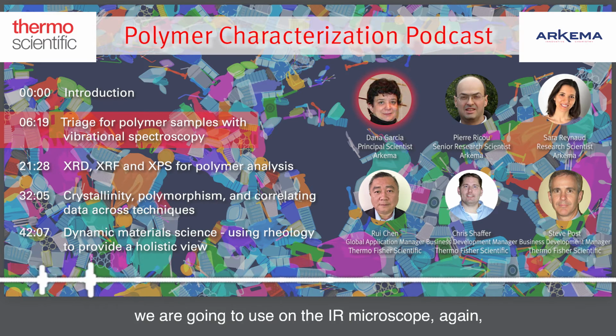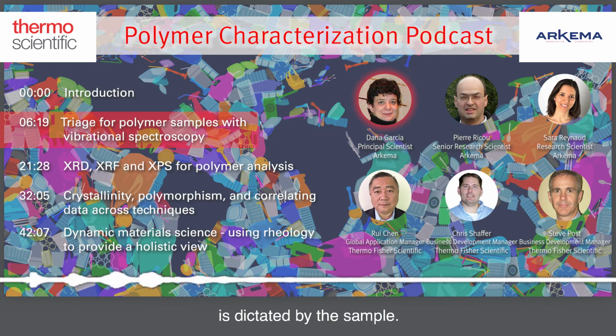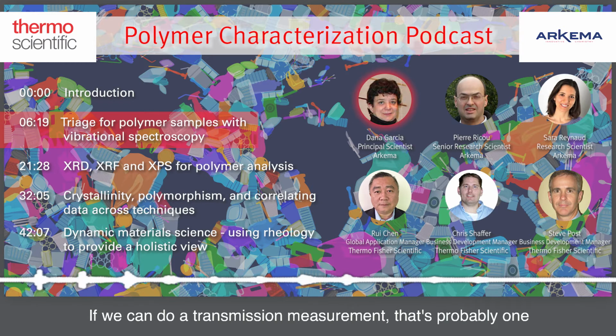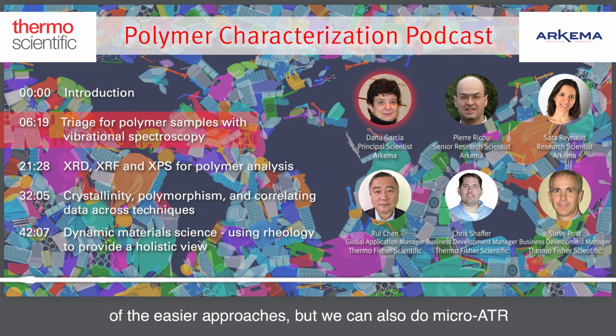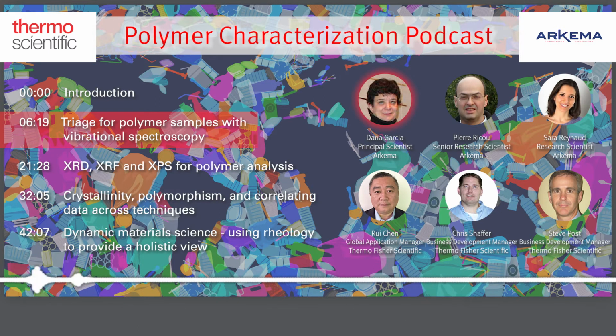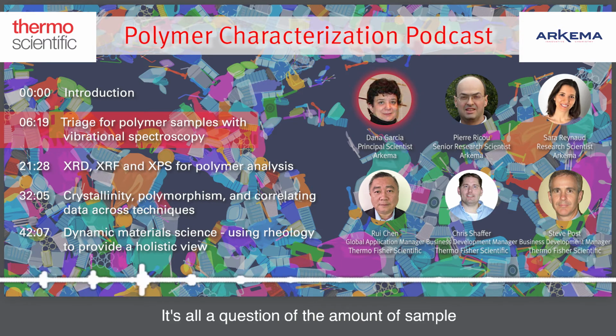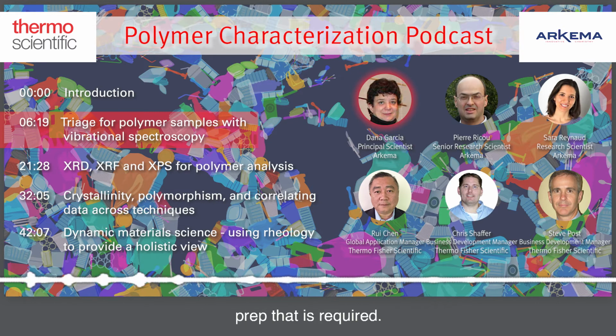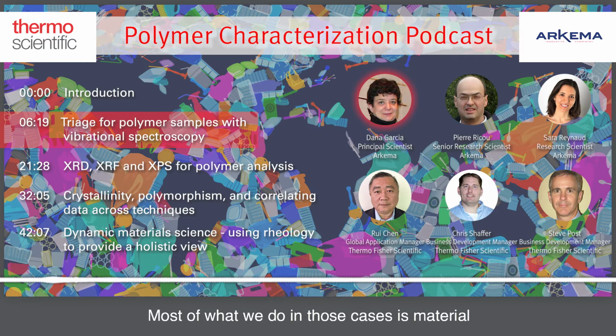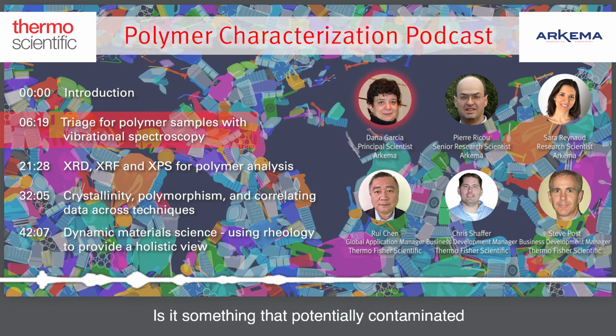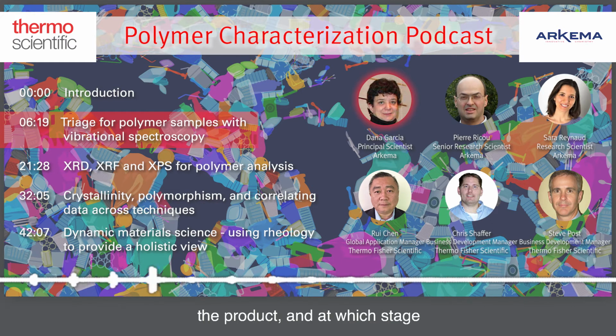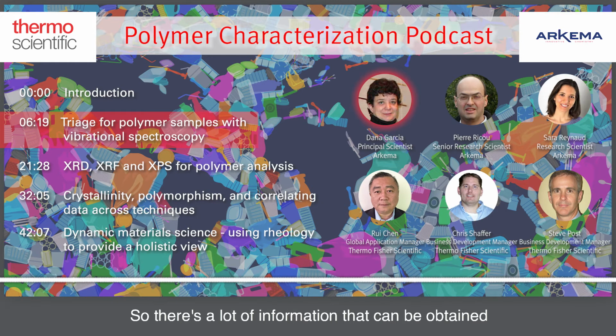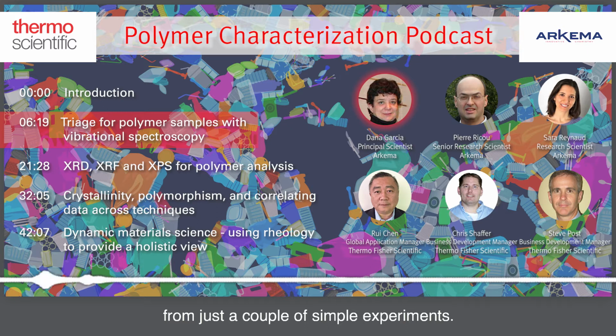And the technique we are going to use on the IR microscope, again, is dictated by the sample. If we can do a transmission measurement, that's probably one of the easier approaches, but we can also do micro ATR and micro reflectance. It's all a question of the amount of sample prep that is required. Most of what we do in those cases is material identification. What is the defect? Can you infer its origin? Is it something that potentially contaminated the product? And at which stage the contamination occurred? So there's a lot of information that can be obtained from just a couple of simple experiments.